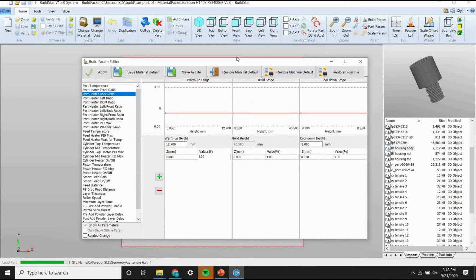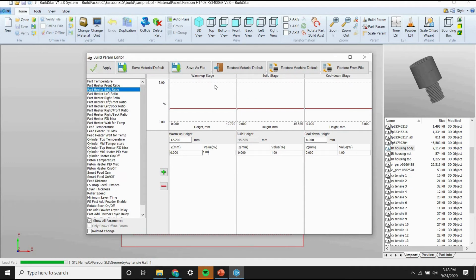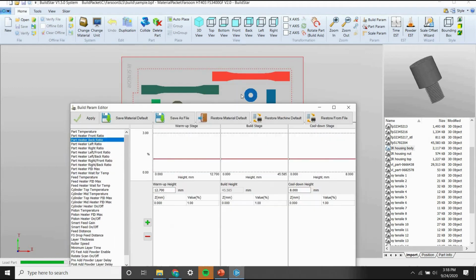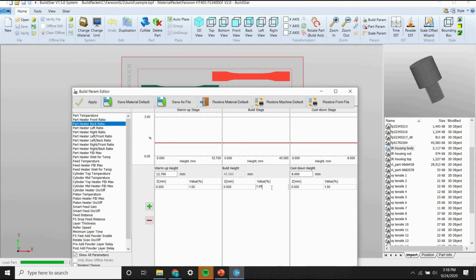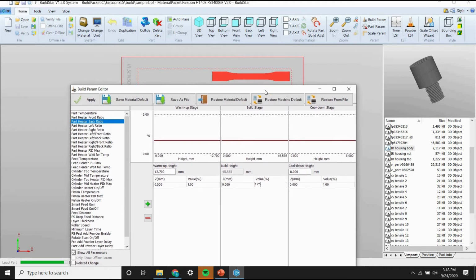As you can see in our build parameter editor, we have columns for warm up, build stage, and cool down stage. And we're actually able to change the percentage for each stage. So in the build stage, we would want to change this to 1.25. I usually like to let the build run a couple layers just to make sure that it's absorbing that change in temperature, either if you're raising or lowering the heater ratios. And if that fixes the area, then that's all you have to do.